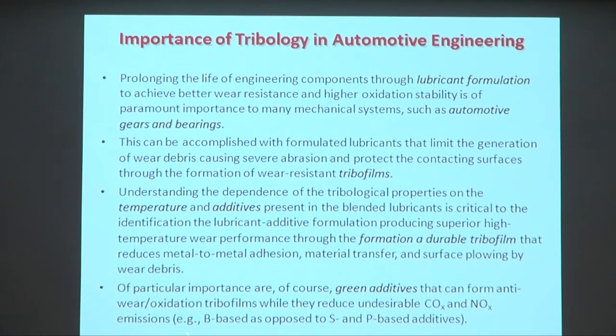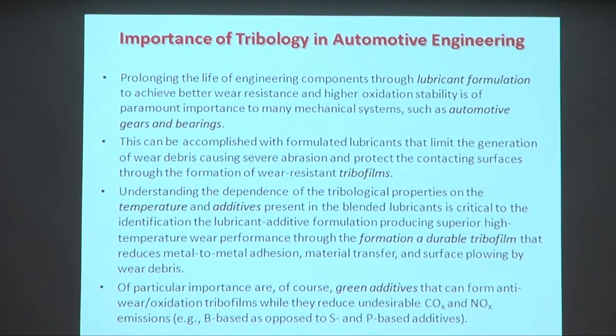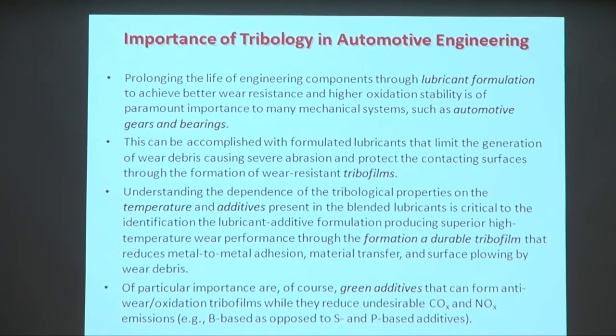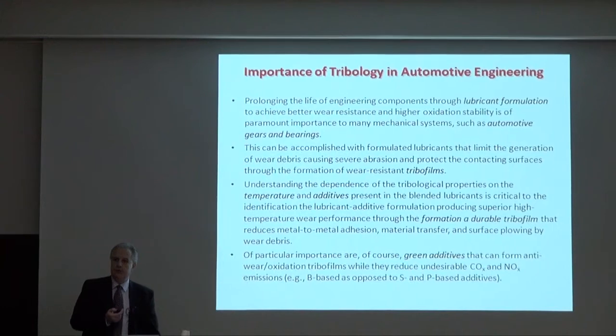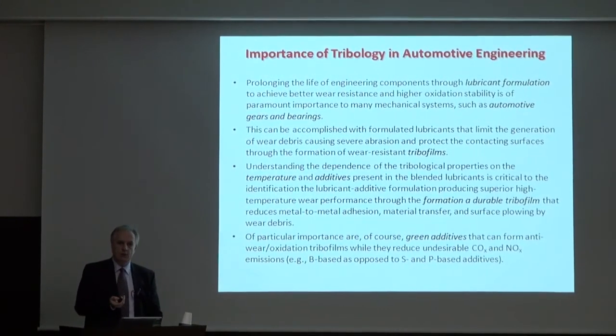And so an example that you will see me presenting today is to use boron instead of phosphorus. We've seen earlier that reducing by half the content of phosphorus is a major step in that direction. Let me give you a very quick reasoning of why we use phosphorus and sulfur and what role they play, which will become more obvious later. Sulfur forms sulfides and sulfates, which are easily shearable phases. If we have those in the tribofilm, we'll produce low friction. Phosphorus forms hard, glassy phases, which provide the wear protection in the tribofilm. So the tribofilm is a biphasic material made of soft and hard phases that synergistically provide low friction and wear resistance. But because of the softer phase, it's going to wear out, and that's why it is referred to as a sacrificial film.